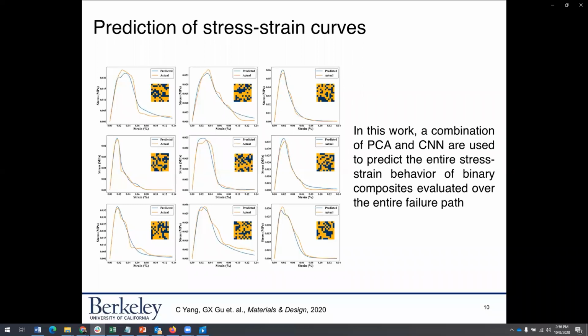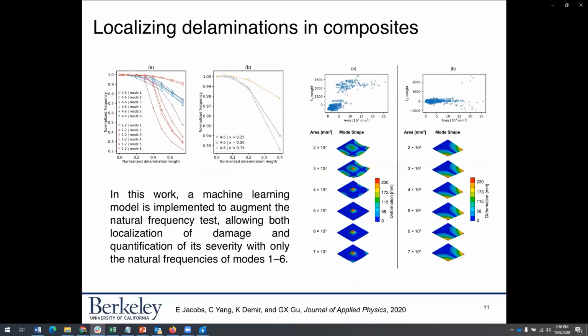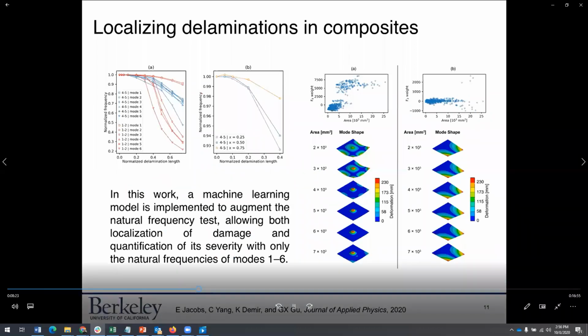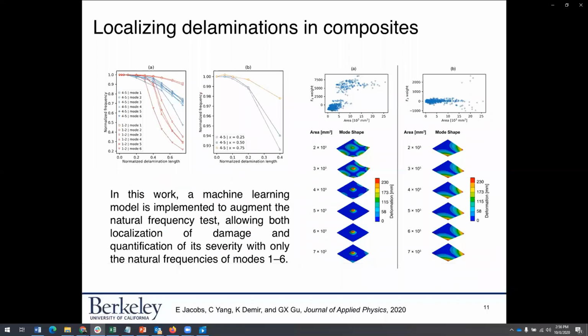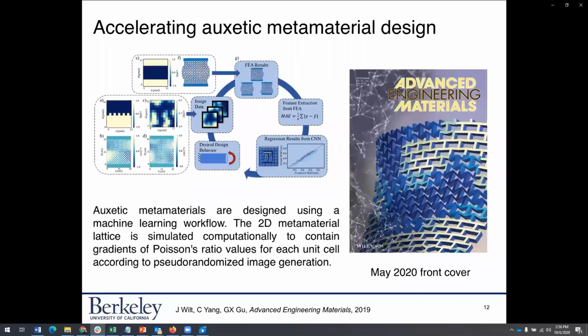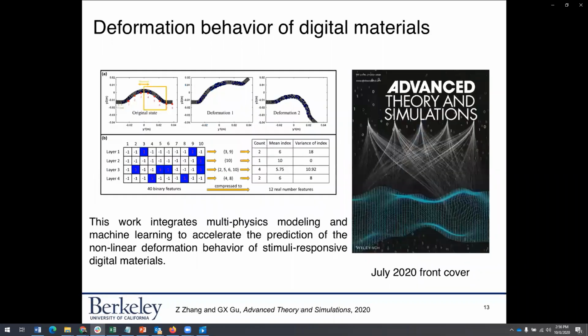Another very interesting application is to use machine learning to predict failure in materials, such as delamination in composites. In this work, a machine learning model is implemented to augment the natural frequency test, allowing both localization of damage and also quantification of its severity. We were able to interpret our model and discover a phase transition for natural frequencies with different size delaminations. We have also applied ML to exotic metamaterials and to predicting the deformation behavior of digital materials as well.